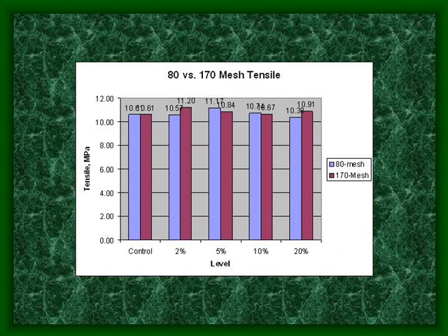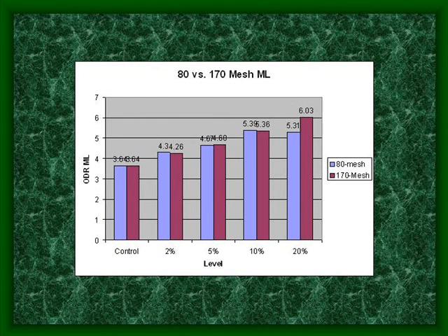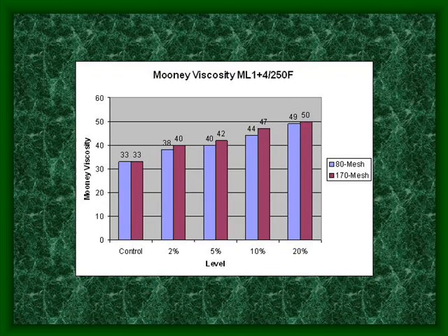Here's a side-by-side comparison of the tensile strength in this experiment. As you can see, there are really pretty minimal differences in tensile strength, even at the higher loadings between these two materials. In ML, the loading effect we noted earlier was similar in both of the samples. The Mooney viscosity values, ML 1+4 at 250 F, also reflect this increased viscosity with increased loading.